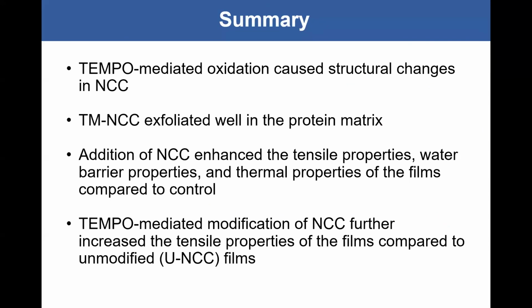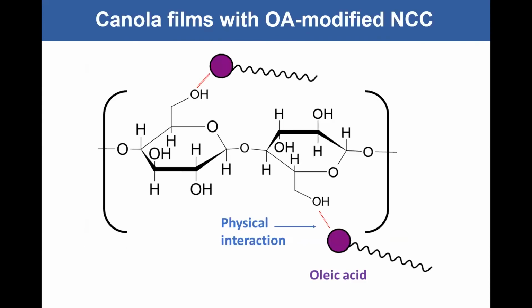canola protein-based films. I'm going to go into the other experiment very quickly with the time limitation, just to show you what we are doing right now, because as I mentioned earlier, the water barrier properties were not great when it comes to the TEMPO modified extractions. So what we did was we grafted oleic acid onto nanocellulose, a hydrophobic long chain hydrocarbon fatty acid, in order to further improve the hydrophobicity of the materials.